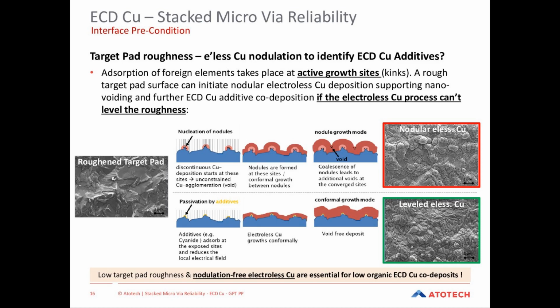What we found is in general that rough surfaces are more prone to adsorb plating additives, and this is of course something we should avoid. That means the rougher a target pad of the microwire interfaces is, the more adsorption of additives you will have. So the first learning from this experiment was to keep the target pad roughness low. Roughness can help to clean a surface. So roughening the surface cleans a surface, and a rough surface gives for sure a better mechanical bond. But on the other hand, it is always a trade-off with more adsorption of additives on such rough surfaces. So the target pad roughness should not be too high.